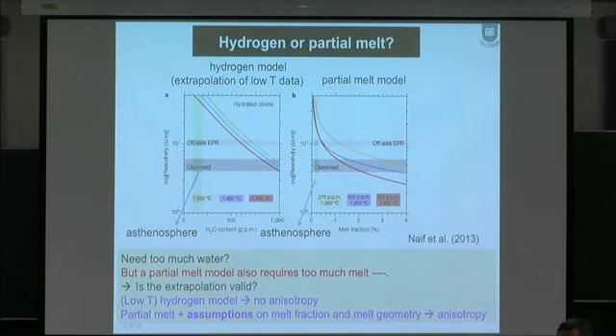Then I'm going to show you in the next few slides that calculation of water content based on limited laboratory data is not quite justifiable, because what they did was they used low temperature conductivity data, then extrapolated to the asthenosphere temperature to conclude that the conductivity you predict is too low, so therefore you need lots of water. I would argue this extrapolation is not quite appropriate if you look at a little bit of the physics of electrical conductivity.